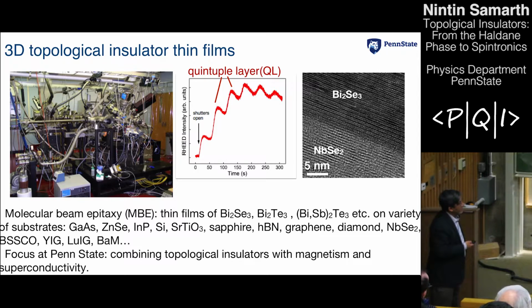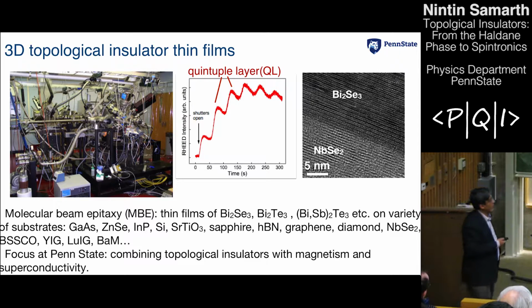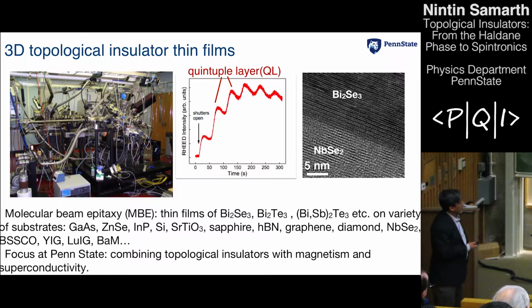We can then slice the samples and use electron microscopy to look at the structure of these samples. This is some topological insulator, bismuth selenide grown on a superconductor, niobium diselenide, and you can make reasonable structures, right? So we've been able to grow these kinds of thin films on a variety of substrates that are all listed over here. And unless you're a condensed matter physicist, you don't particularly care what all these substrates are. But just what I want to get across is that we can combine these materials with magnetism and superconductivity of different kinds of materials. Okay.